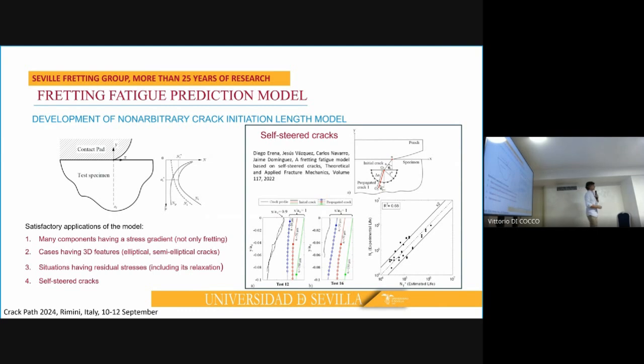This model has been applied with very good results in many situations. For example, components having a stress gradient, not only fretting, cases having 3D problems, like elliptical or semi-elliptical cracks, situations having residual stress, also including its relaxation, and self-steered cracks. For me, special mention is required for the last case, when the cracks are self-steered. In that situation, in both phases, in the crack initiation and in the crack propagation phases, the cracks dictated by the model are self-steered. This model produced very good results in terms of the fatigue life predicted, but also are very important in terms of the crack path predicted. We can see here the experimental crack path, and we can see here the different crack path prediction by the model.